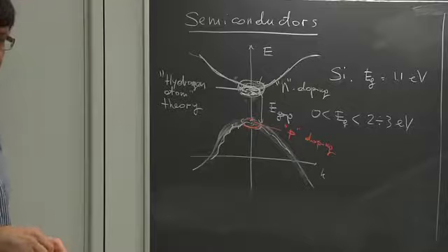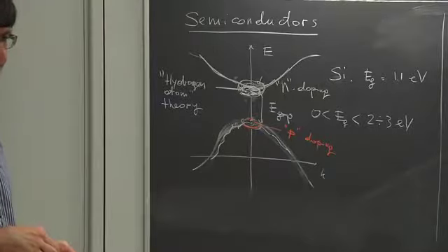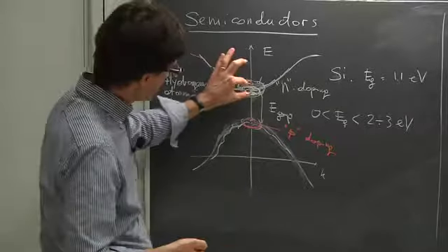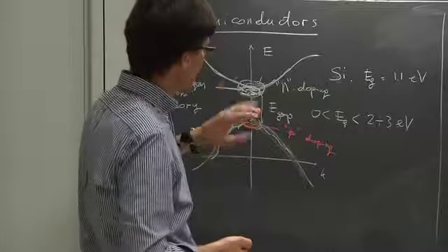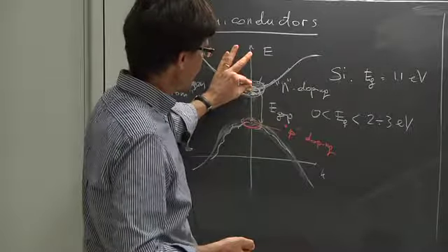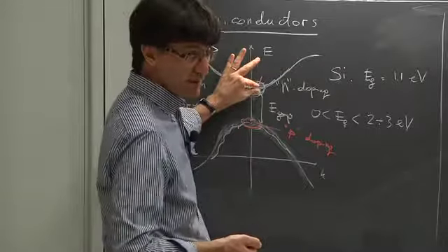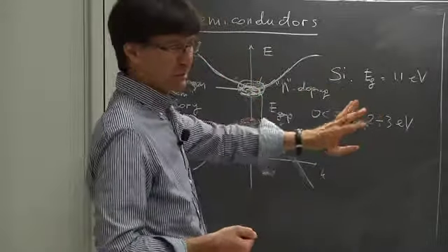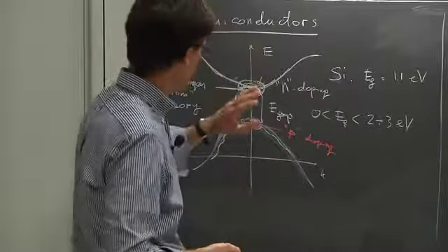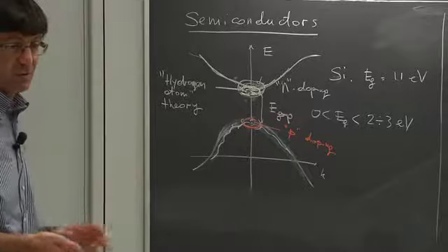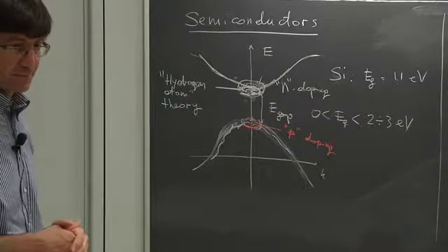Yes? When we introduce impurities, does it change the energy gap? By a little, because you're perturbing. You're changing it by an amount which is extremely small, because for perturbation theory to hold it must be small. Otherwise, if it's too big, the perturbation theory doesn't hold. So they change the band gap, but by a small amount, of the order of milli-electron volts, compared to a value, say, of 1 electron volt. It's nothing.